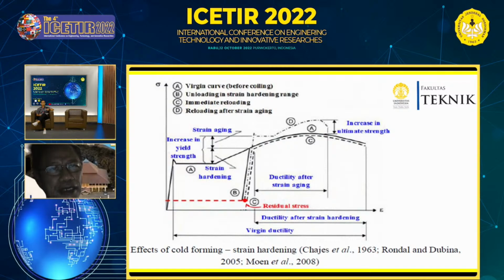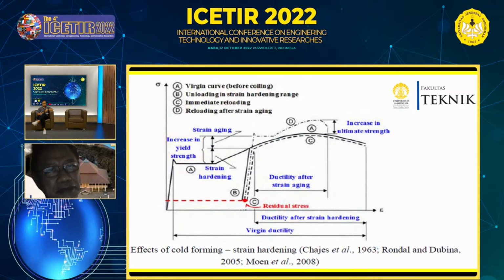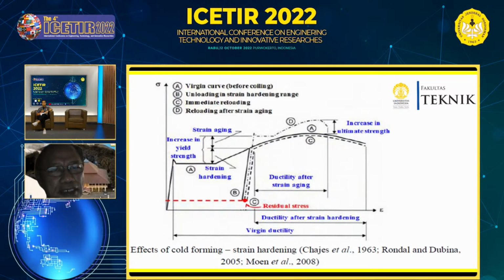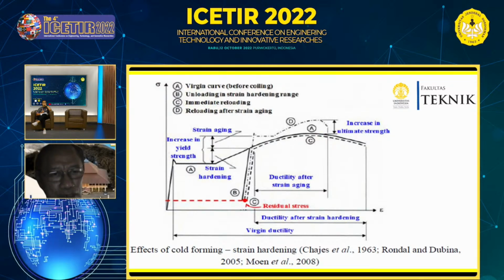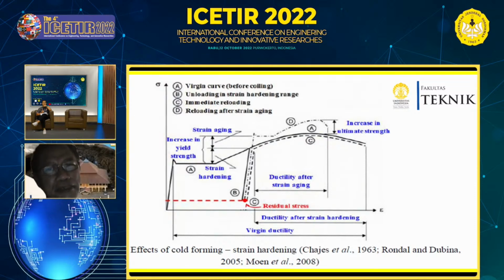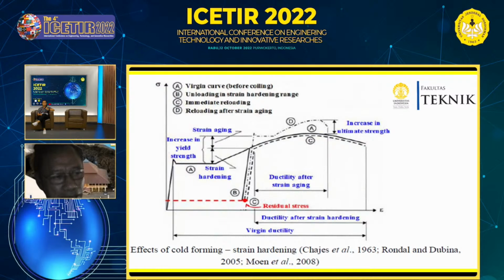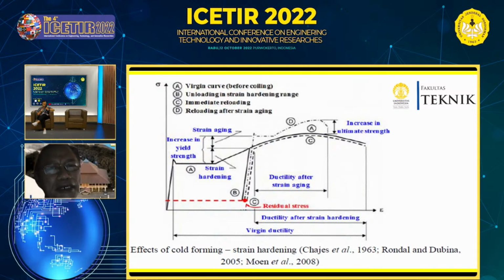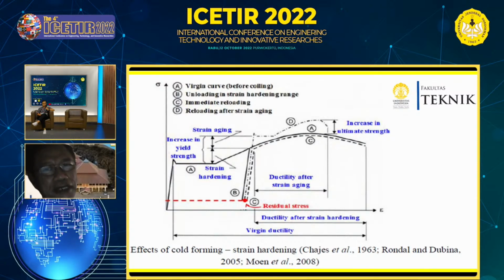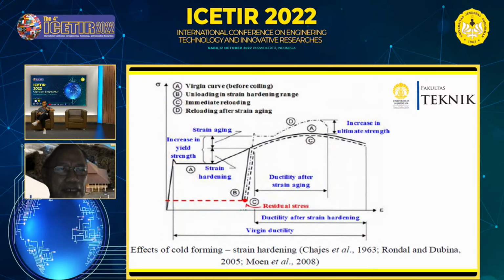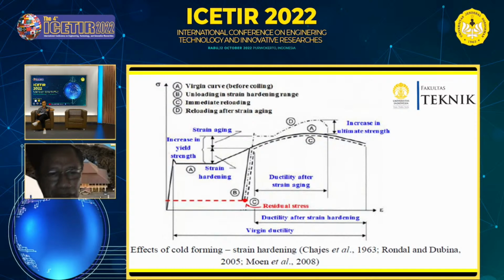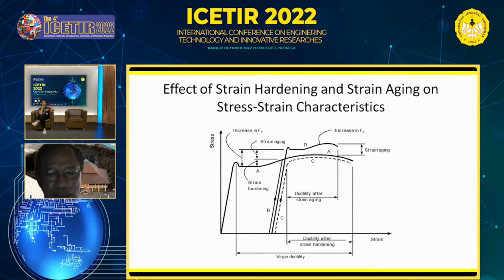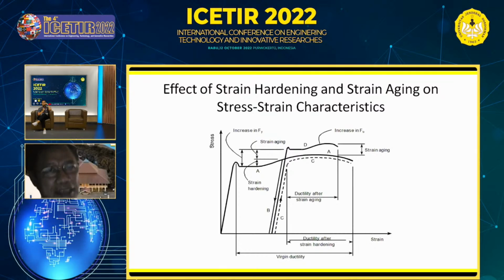But if we reload after what is called strain aging, we will have an increase in ultimate strength. It can be seen that after unloading, we wait for some time, depending on the temperature, and we do not reload immediately. Then we will have strain aging, and the curve will take the D line. So we have an increase in ultimate strength, but this technique creates a residual stress. If we ignore or erase the residual stress part, we come to this stress-strain relationship.